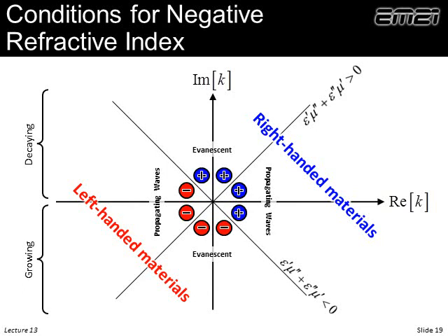But notice if we have just a single negative material, this equation implies we have to have loss in order to be left-handed. It comes from that equation. Now, if both are negative, certainly we see experimentally that our metamaterials are still lossy, but in principle, they don't have to have loss to be left-handed.